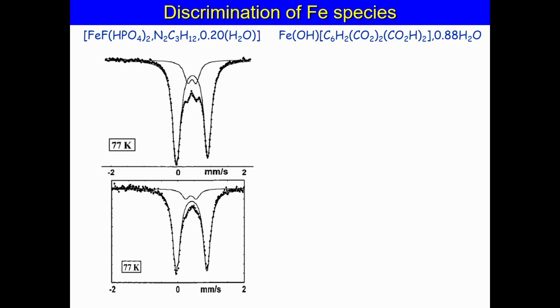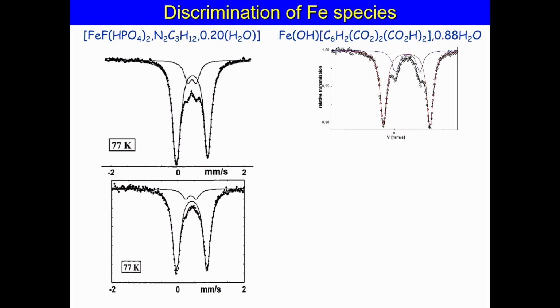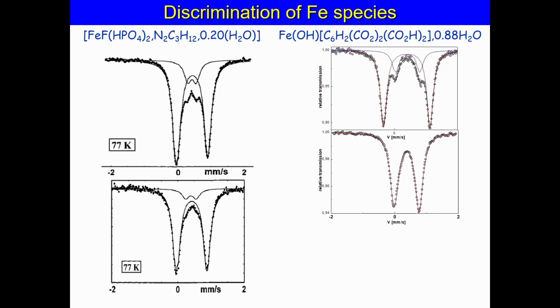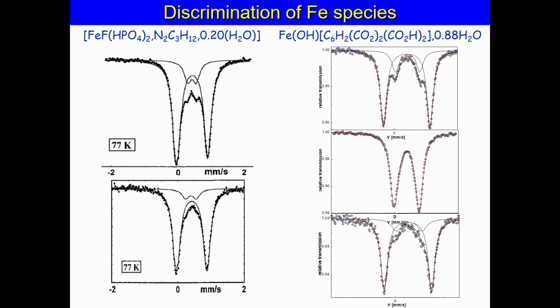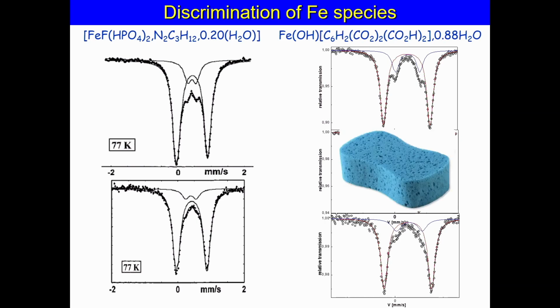One day after, we made another spectrum, and the spectrum was rather the same as the first one. That means the system was taking up water and expelling it, according to the treatment. The other one is another sample. After treatment, you see that the minor component remains and the major component disappeared, the opposite situation. And after, it was possible to obtain rather the same spectrum. So this one was full of water molecules, which X-ray diffraction was not able to detect.